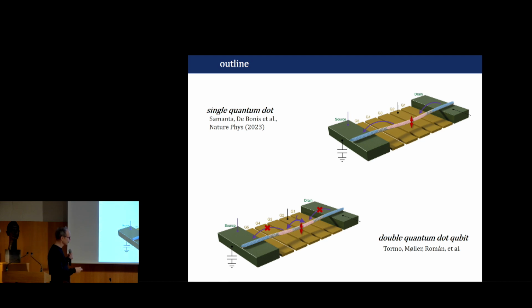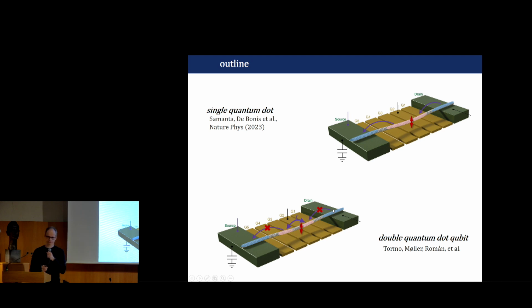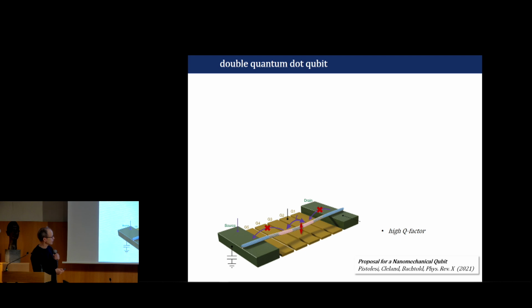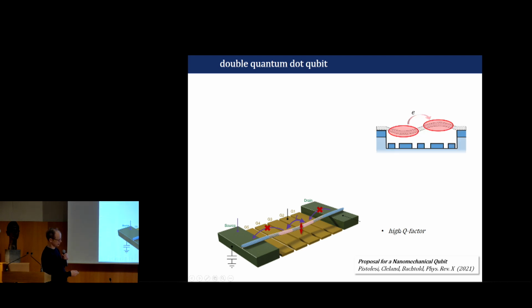And things are different when you work here with two dots in pink, so here and here. And so the electron is tunneling between these two dots, and it doesn't go in the electron reservoir. And things are much better. So in the experiment, we work with a nanotube resonator that can have a quality factor up to 10 million. And so here, the vibrations modulate the electron distribution between the left and the right dot. And you see that this is nice, because the electron does not go in the reservoir where you have losses.